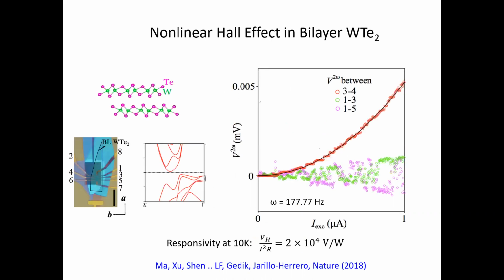So the first experiments on this nonlinear Hall effect came in 2018 from my colleagues at MIT, Nuh Gedik and Pablo. They came up with the idea that this effect could be present in this atomically thin crystal, tungsten ditelluride. This crystal has a very low symmetry. It has a polar axis within the ab plane. And also the DFT band structure calculation shows that the band dispersion at least qualitatively resembles this tilted Dirac fermion that I just showed you.